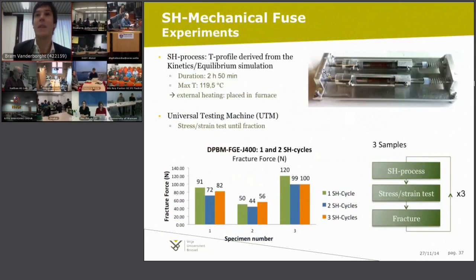And then we did it in a universal testing machine. We measured at which force we could break the element. Then we put it in a furnace to do the self-healing process, and then we broke it again, put it again in the furnace, broke it again, and so on.